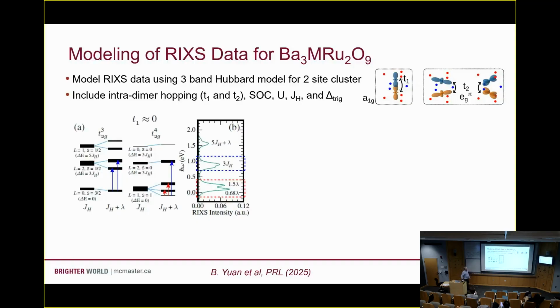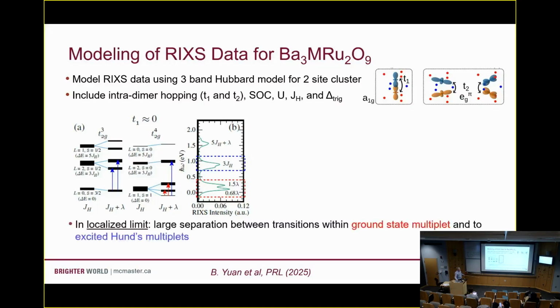Okay? So you can start by looking at the RIXS spectra in the localized limit. Okay? So before we do any complicated calculations, we want to convince ourselves that the simple model doesn't work. And so if there is no intradimer hopping, for this T1 equals 0 limit, then we basically get one ruthenium that has 3 valence electrons, one that has 4 valence electrons. Okay? And in the D4 case, we get this splitting as before into J equals 0, 1, and 2. Here it's J effective 3 halves and 1 half. And we can look at the resulting RIXS spectra here. You can see that you get 1 band excitations here, 1 band here. This does not look like what we're measuring. Okay? The localized model is clearly insufficient.